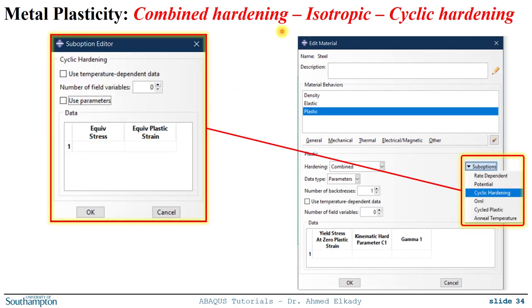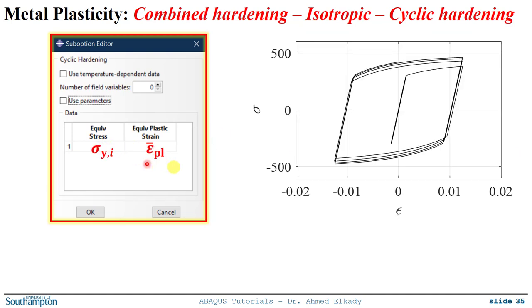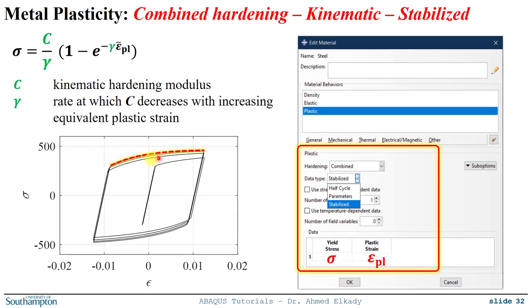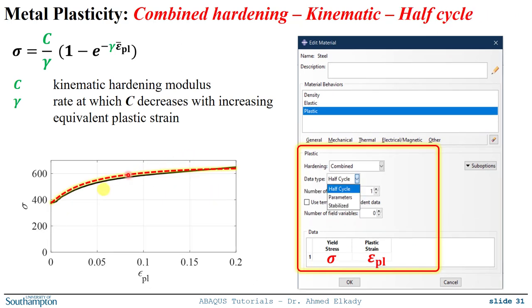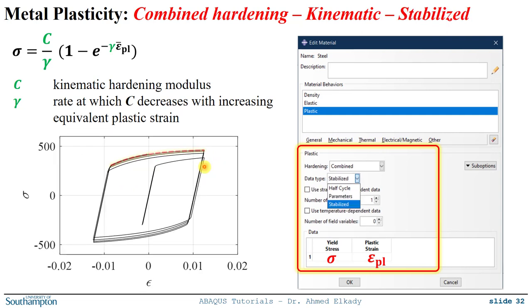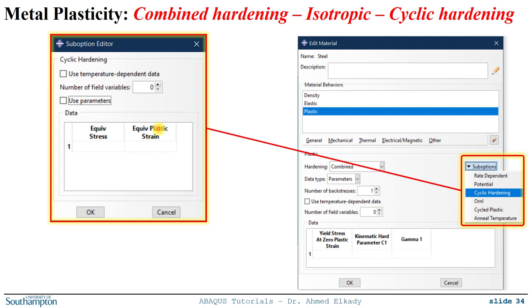The next thing for the combined hardening rule is to define the isotropic component, which you can access here from the suboptions, and then you can select cyclic hardening. When you do that, you will get this window, which is asking you to provide the equivalent stress and the equivalent plastic strain. These are different from the ones we used to get from the stabilized curve or the half cycle. The equivalent plastic strain in ABAQUS is called PEEQ, the symbol for the field variable, and this is the equivalent stress.